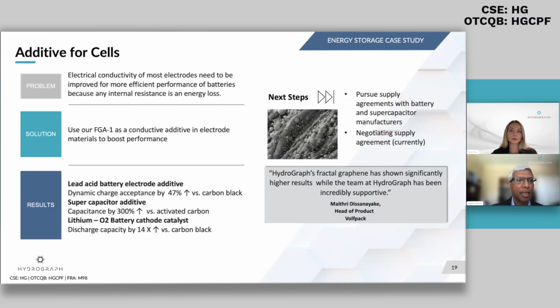So we are on to the next slide now. It's on the energy storage, where we have gained performance enhancement by small addition of the material. If you look at lithium-ion batteries or lead-acid batteries or future technologies like lithium oxygen or lithium air battery, all of these have one thing in common, that's the electrode material, which is an active material mixed with some conducting particles to make it electrically conducting. Because without the electrical conductivity, when the current goes through the device, it just gets wasted to heat, and that's a loss mechanism. So we want to minimize that loss by improving the conductivity.